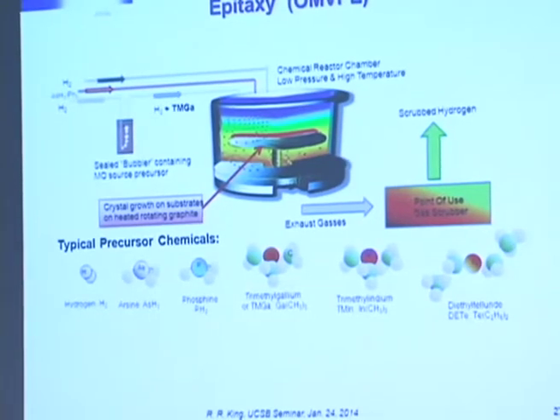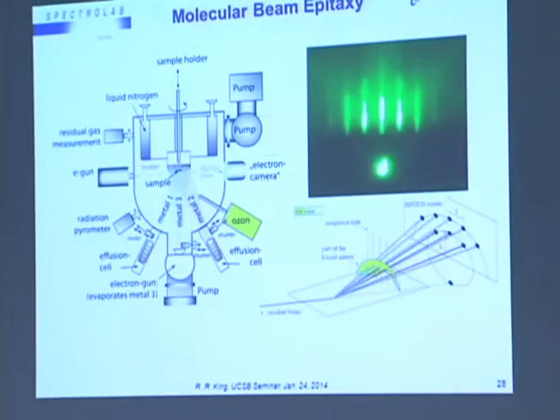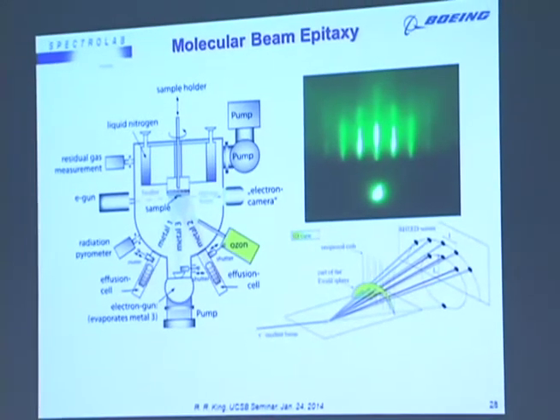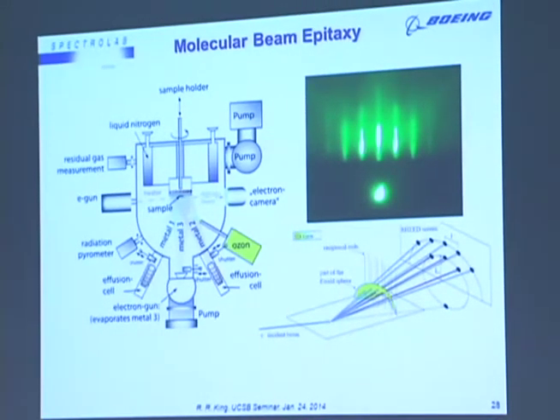So one of the main ways that we've used at Spectrolab to grow our materials is organometallic vapor phase epitaxy, or as many people like to call it, metal organic chemical vapor deposition, or MOCVD. I think many people are very familiar with this process. We introduce our metals in the form of organometallics. Molecular beam epitaxy, of course, is very useful for very controlled samples, and we can monitor the layers growing one atomic layer at a time through RHEED patterns such as this.